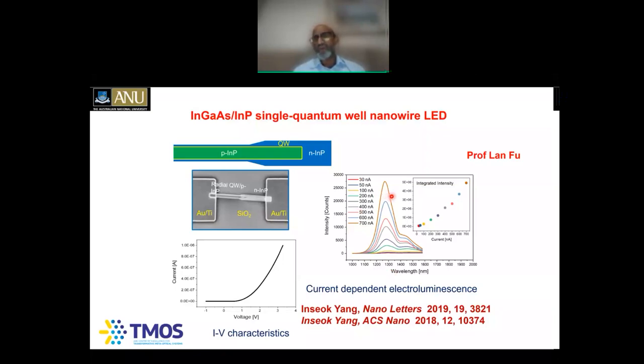There are also two peaks here, one peak here and one peak here. That's mainly because there's a quantum well sitting on the top here, the axial quantum well, which is emitting at this wavelength, and the radial quantum well, which is here, and that's emitting at this wavelength.